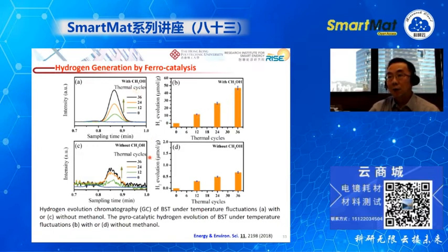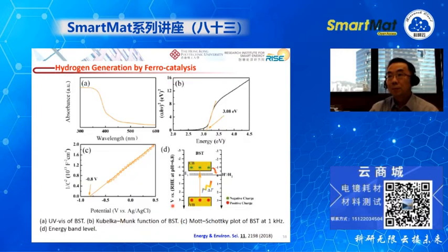hydrogen evolution. The reason for the enhancement is that the methanol is actually a hole scavenger. So it can effectively capture the holes generated during the thermal cycling and reduce the charge recombination between electrons and holes, and therefore we can greatly enhance the hydrogen evolution. We also characterize its band structure by using a spectroscopy method, and we found the band gap of this barium strontium titanate is around 3.08 eV, and the conduction band of the BST is more negative than the hydrogen redox potential. So any electrons in the conduction band will be able to participate in the hydrogen evolution reaction.